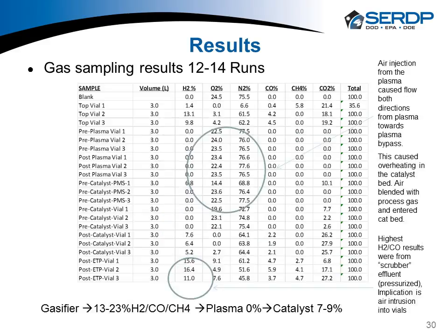December, after we had everything fixed and back together, we had another series of runs. Again, this is where we had the air from the plasma causing flow in both directions, and you can see that because we see all this extra oxygen in there. We see very little hydrogen. Then going into the catalyst, again, most of the data showed there's very little hydrogen, a lot of oxygen. And then coming out of the catalyst, for a couple of the runs, we did see significant amounts of hydrogen coming out, very little methane and some carbon monoxide.